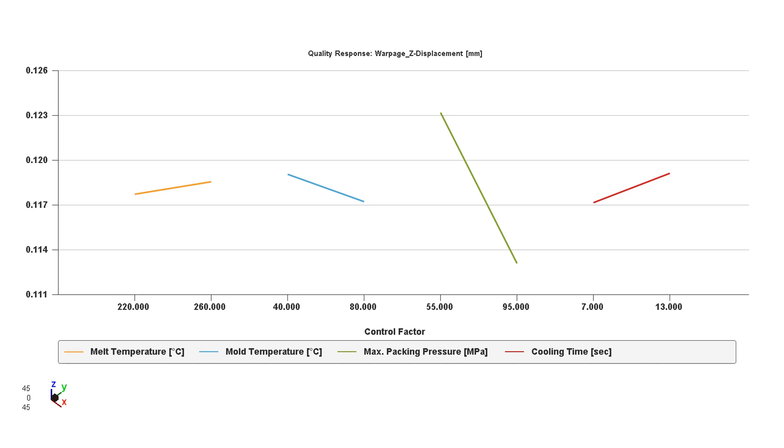What is not so obvious is the one all the way to the right, which is the cooling time between the low cooling time of 7 and the high cooling time of 13. So why is it apparent that at a lower cooling time we get a flattest part? Remember what happens in the molding cycle during the cooling phase. If we have a long cooling time, we can actually create molded in stresses and the mold works like a fixture. When the part comes out of the mold and it has a lot of molded in stress, this fixture of the mold is not longer there and the molded in stress, if it's high, can warp the part a little bit more than under a shorter cooling time.